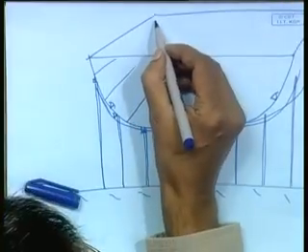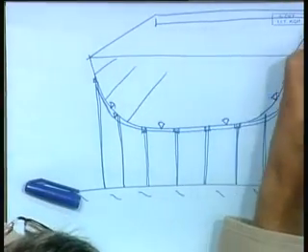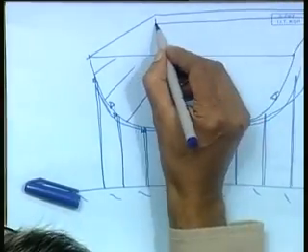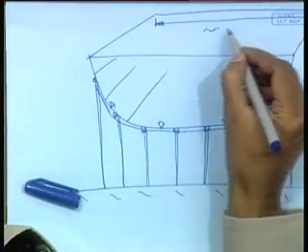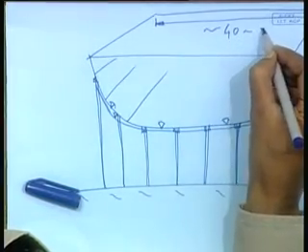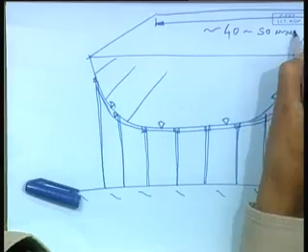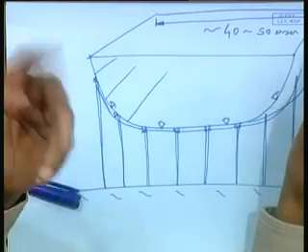Once you shift it there and bring in the other components, you might find they are not matching. Why? You may find that this length has become short, it has shrunk. It may shrink as much as 40 to 50 millimeter. You won't be able to even make it out with the naked eye.